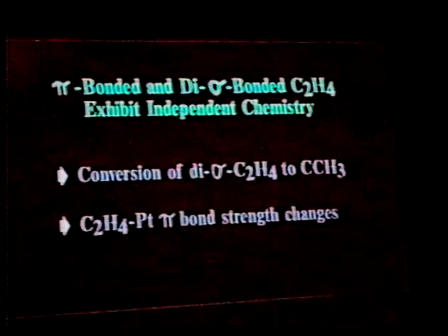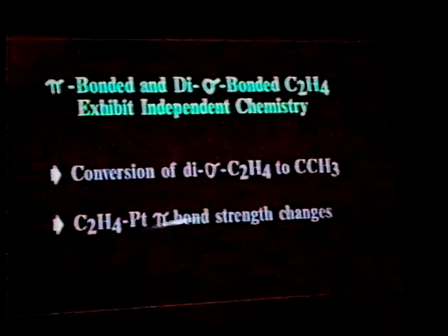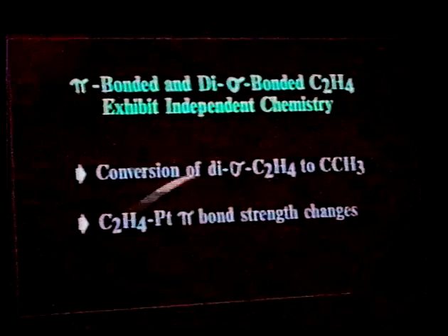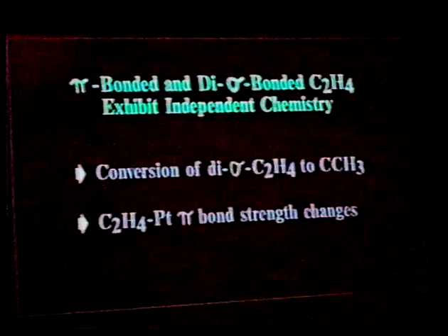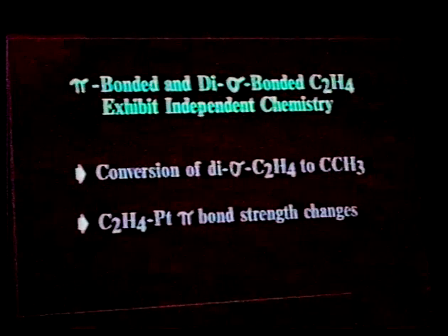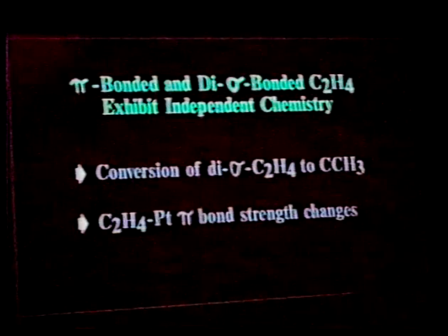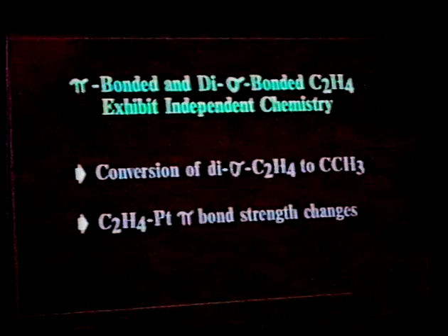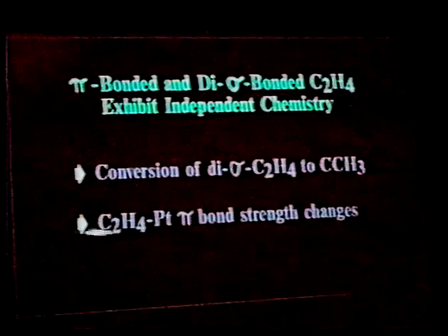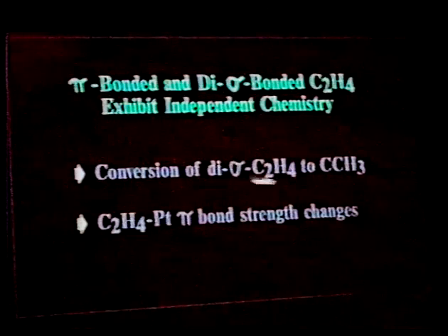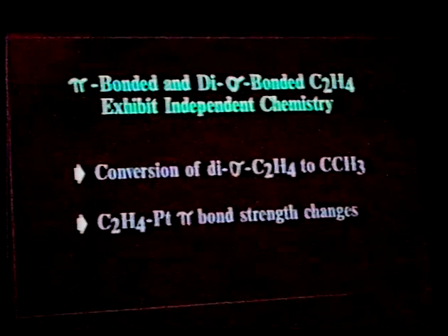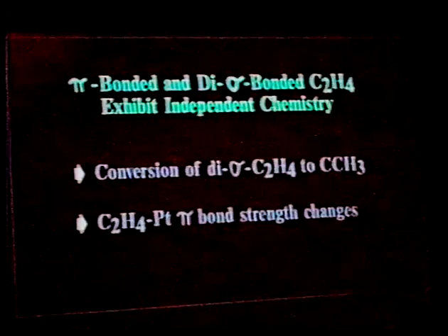Now, related to that then is that what we find is that we can change the strength with which the pi-bonded species adheres to a platinum particle just in the way in which we pre-treat the catalyst. And while we observe these changes, again now, the ethylidyne, or the disigma-bonded species, appears to be operating completely independently.